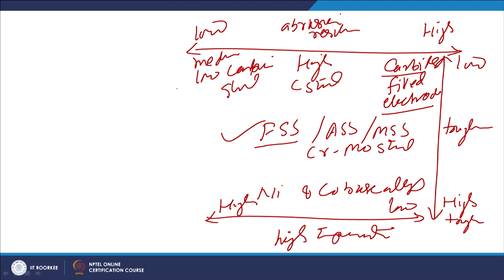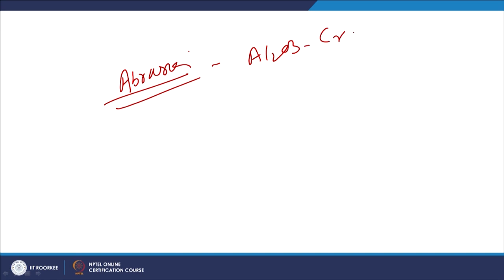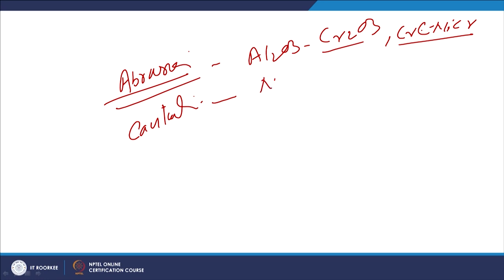Now here I will write some of the materials for a variety of applications. For abrasion conditions, if the abrasion conditions are being experienced by the component, then coatings of alumina and chromium oxide Cr2O3, the chromium carbide and the nickel chromium systems are used, and for cavitation erosion conditions, nickel titanium, copper nickel, and AISI 316 stainless steel and cobalt, chromium, tungsten, carbon systems are used for cavitation resistant applications.